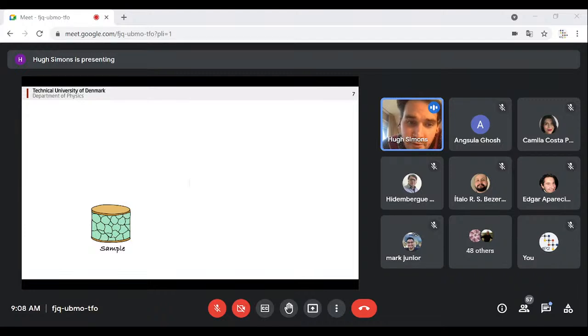And so the way dark field microscopy works is this, and this is where it's really essential that you can see my screen. So the idea is that generally we start with some bulk sample. The sample can be millimeters in size, and it can be a single crystal, a film, or in this case, a polycrystal. So you imagine a polycrystal, for example, with many crystalline grains in it. And what we do is we use a series of optics to illuminate the entire sample using a very intense beam of hard X-rays.